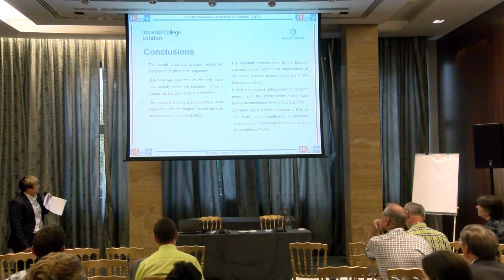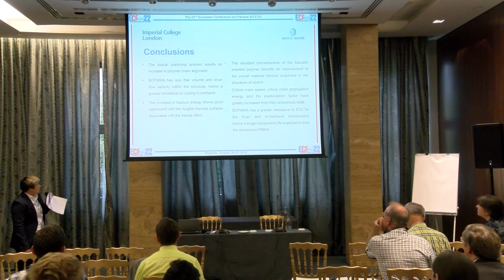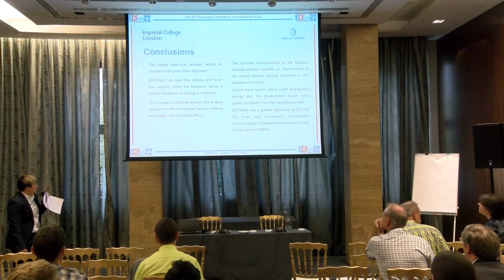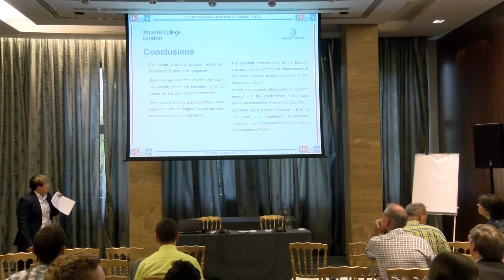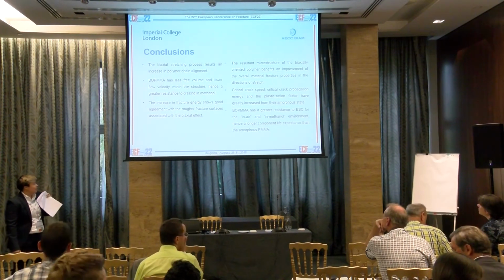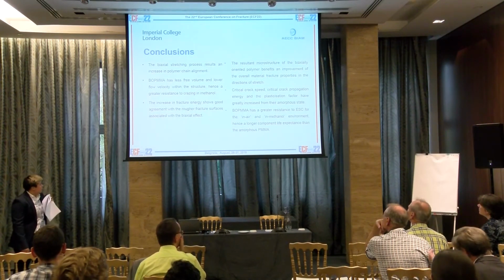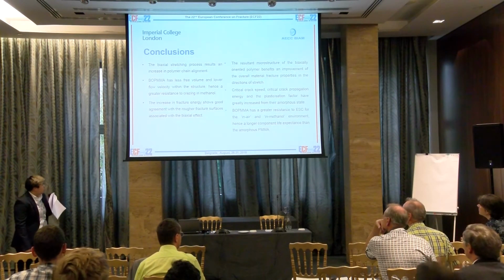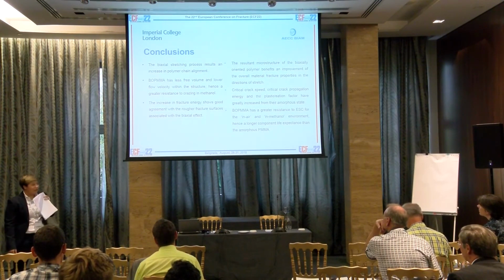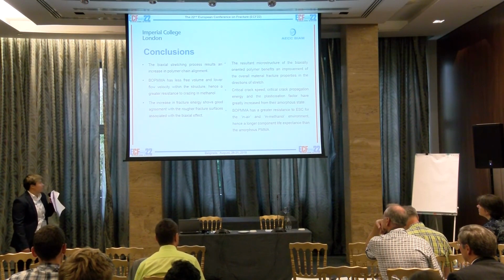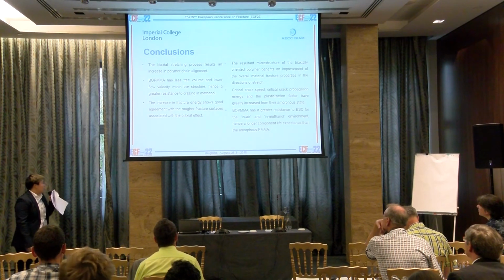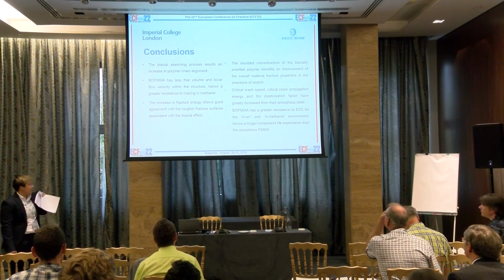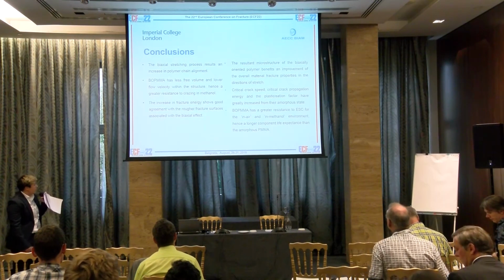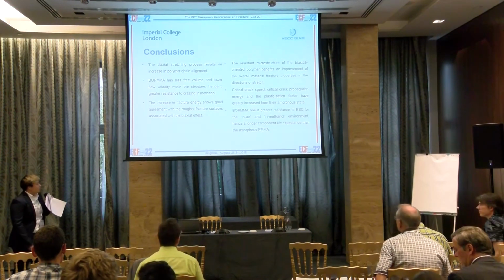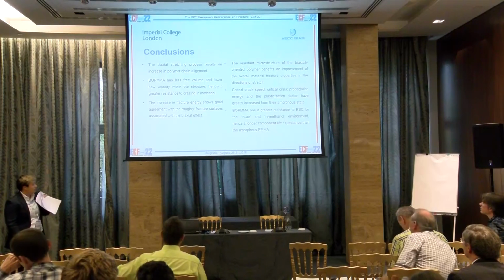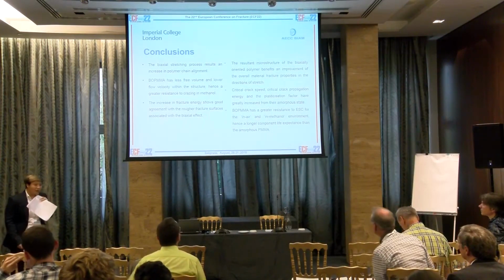The resultant microstructure of the biaxially orientated PMMA benefits an improvement of the overall material fracture properties in the direction of stretch. The critical crack speed, critical crack propagation energy, and the plasticization factor have greatly increased from the amorphous state. And lastly, BO-PMMA has a greater resistance to ESC for the in-air and in-methanol environments, hence a longer component life expectancy than the amorphous PMMA.